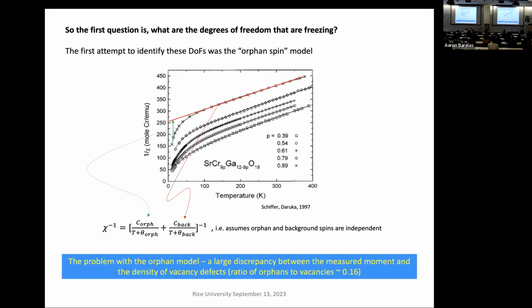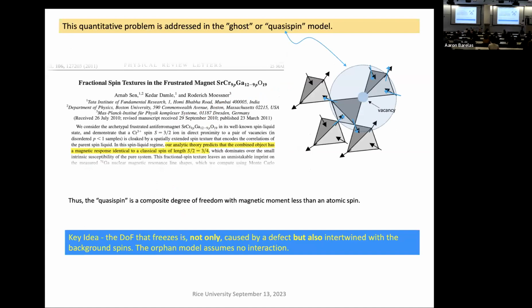Okay. So the problem with this interpretation is that the numerics don't work out. If you ask, okay, how many spins does this represent? It's impossible to relate that to the chemistry of how many defects you put in, which doesn't seem right. And so this quantitative problem is solved by the so-called quasi-spin model, in which it was shown by Messio and folks that a spin vacancy, in the systems I'm talking about, that are usually tetrahedra connected at their vertices, will cause a sort of shielding effect among its neighbors, and from far away this will look like a type of spin, not an atomic spin, but one that has a somewhat reduced moment, half, something like that.